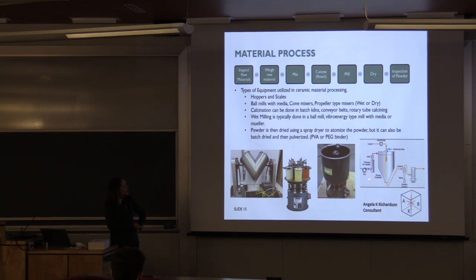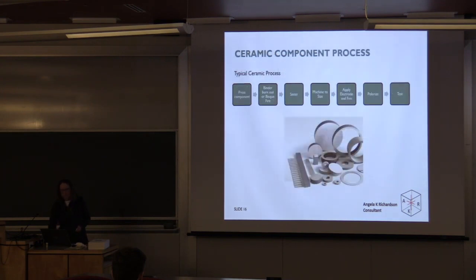Drying can be done by hand, but almost all of the commercial ceramic manufacturers have a spray dryer. In the step of milling here, typically there is an organic binder added, polyvinyl alcohol or polyethylene glycol binder, to assist later on in the compaction of that ceramic. So then after you've got the powder manufactured, you're going to go through the ceramic process. And we'll walk through each of these steps here.